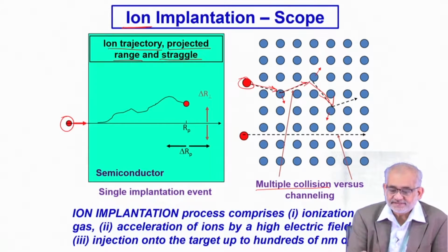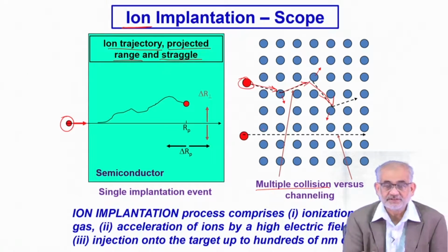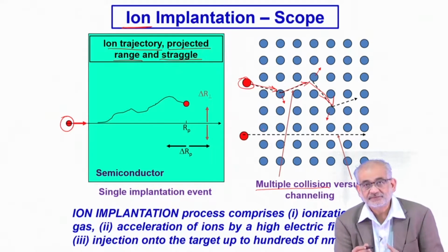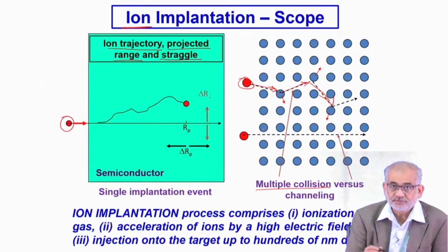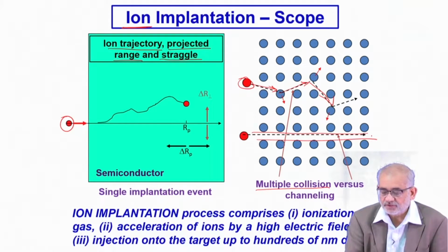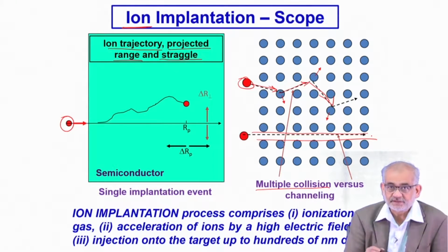But in very rare cases, you have a lattice where the interstitial void size is relatively large, and more importantly, there could be a certain channel which offers a tunnel or pathway for the ions to penetrate deeper inside, depending of course on the crystal lattice that we are dealing with.